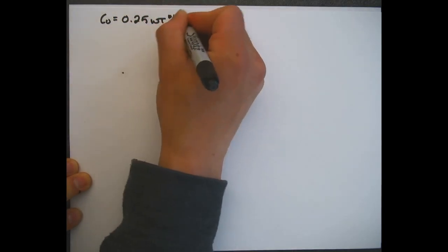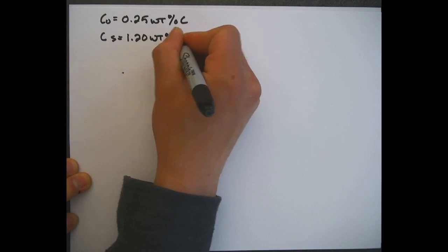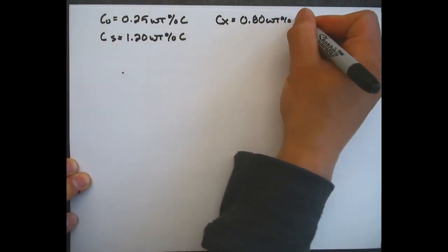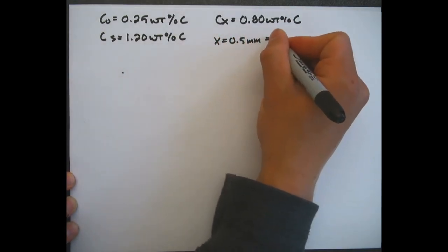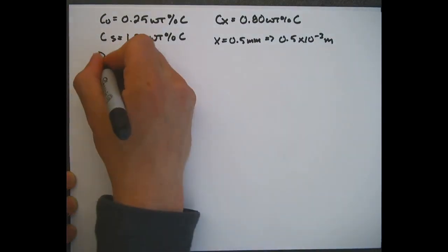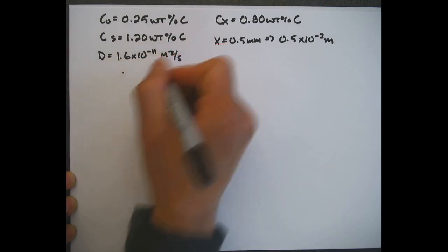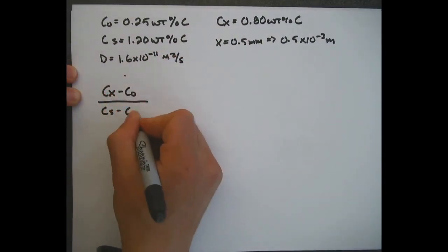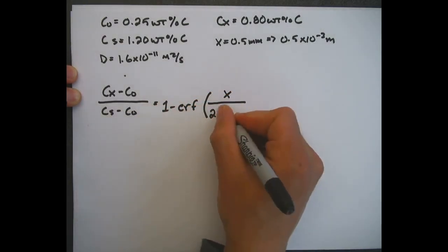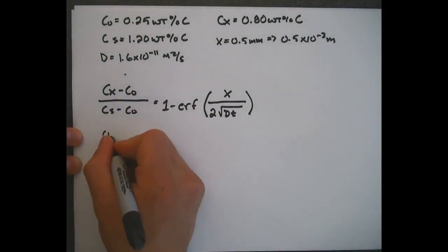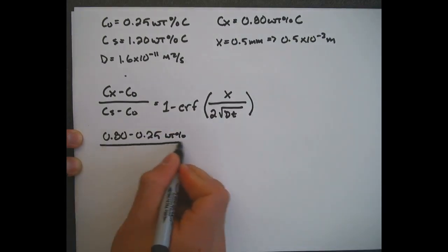Now, picking out details from that story, what we're trying to find is at what time the surface concentration is going to be 1.2%, where the initial concentration is 0.25 weight%, and the concentration is 0.8 weight% at a certain depth of 0.5 millimeters. So we'll give our variables some values: initial is 0.25 weight%, surface concentration is 1.2, concentration at depth is 0.8, and x, the depth that we wanted, is 0.5 millimeters, which is 0.5 times 10 to the negative third meters. Our D for diffusion value is 1.6 times 10 to the negative 11th meters squared per second. Now we have to change x into meters because the units for D include meters, and we want all of this to cancel out, so what we're left with in the end is seconds.